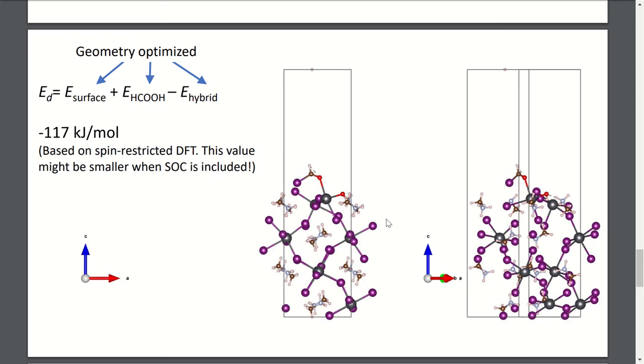For a more detailed exploration of the reaction path, one would try molecular dynamics, as we tried to do last time, but it is more expensive. Here, one goes for a quicker shortcut to do simple things. Basically, what I did here is I have this molecule and I artificially break it into different fragments and attach the different fragments to the surface. Then I compare the binding. It's not the best way, but it is the quickest way, like 100,000 times quicker than the other.